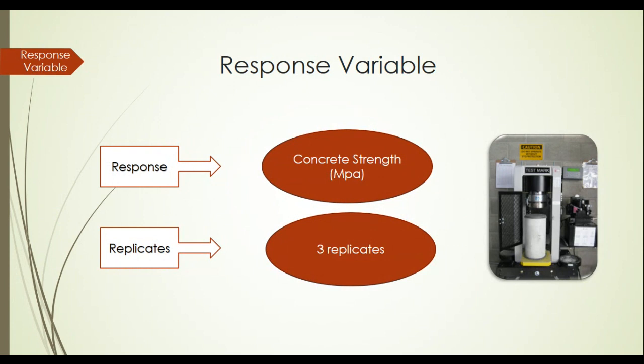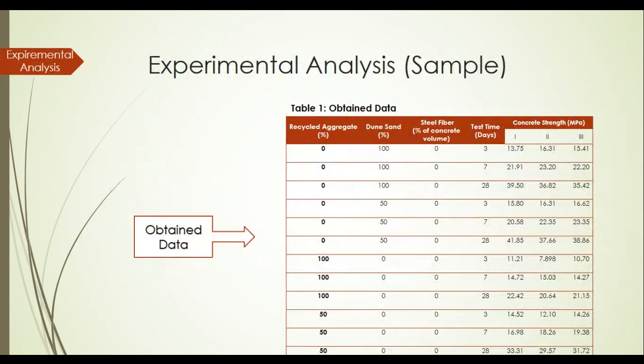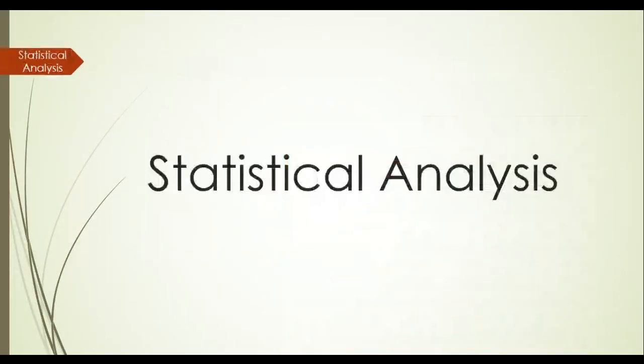To eliminate the error in experimentation, 3 replicates are made and measured for each experiment in our design. Just to demonstrate, here is one sample of experiments that has been done, for example, at zero recycled aggregate, 100% dune sand, 0 steel fiber, and at 3 days tests. We have 3 replicates of this experiment. The first one gives us 13.7 megapascal as a compressive strength, then 16, 15, and the value that we will build our analysis on is the average of these 3 replicates.